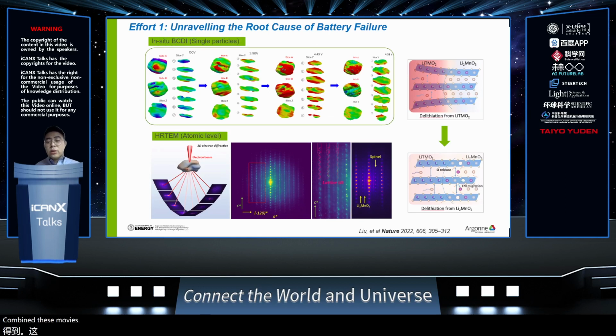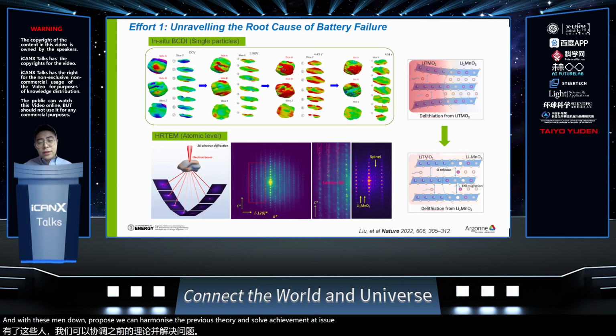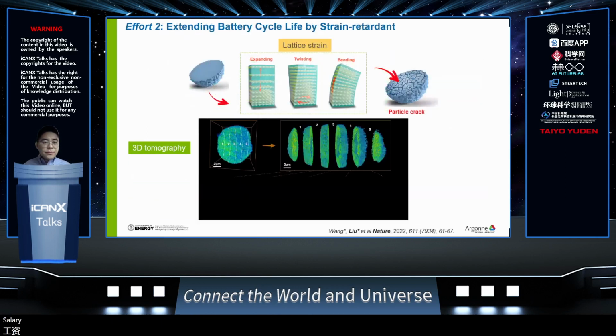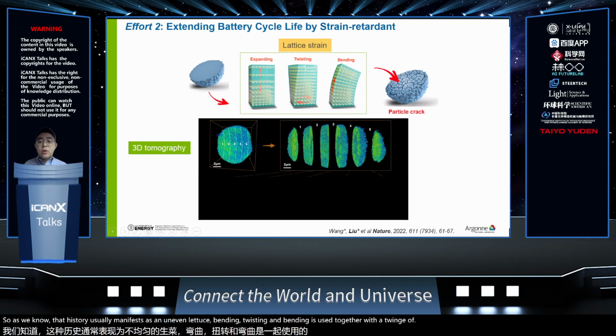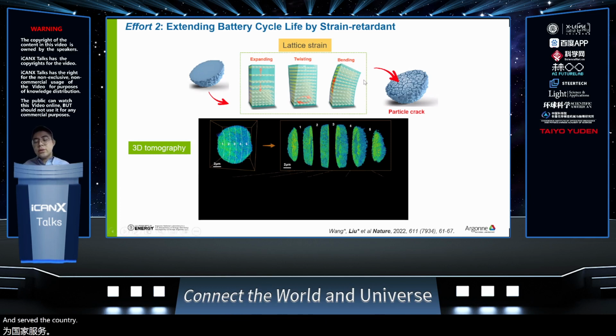Combining these multi-scale characterizations, we for the first time reveal lattice strain is the root cause of battery failure. And with this mechanism proposed, we can harmonize the previous theories and solve the chicken and egg issue in this battery theory. Since lattice strain really damages battery performance, it is particularly important to develop a strategy to solve it. As we know, lattice strain usually manifests as uneven lattice bending and twisting. Together this will trigger particle cracking and accelerate battery degradation.